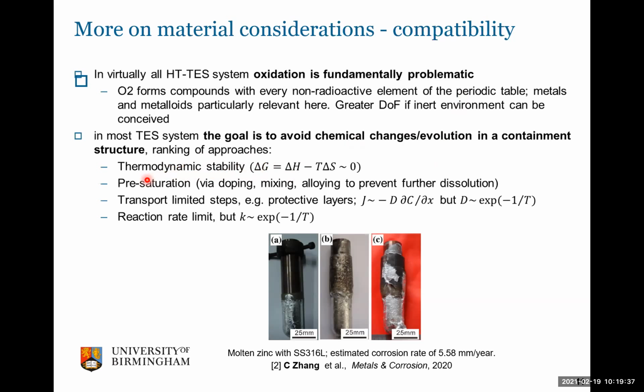Presaturation, this is essentially alloying or mixing the PCM with other components to prevent further dissolution during the operation stages. And then the more commonly used transport-limited steps, which essentially are coatings in a certain way. So here we are trying to minimize the degradation of the containments by essentially playing with Fick's law and reducing as much as possible mass transfer phenomena. Although we have to remember that in general, the diffusivity coefficient increases exponentially with the increase in temperature. So at some point at high temperature, this approach might fail or might not be as suitable as required.